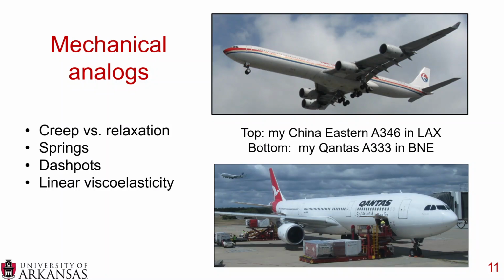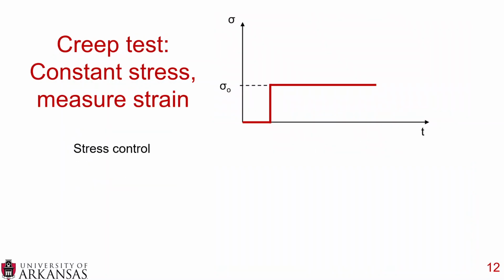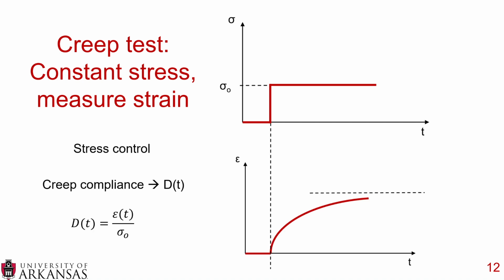Now back to the mechanical analogues, let's talk about creep versus relaxation, and we'll go into springs and dashpots and finish up with linear viscoelasticity. When we think about a creep test, you have a constant stress, and you measure the strain. This is called stress control. Over time, you simply apply some sort of constant stress, and you see what happens to your material. In the world of viscoelasticity, we often relate this with the term creep compliance, which is simply the change in strain over time divided by that initial stress.